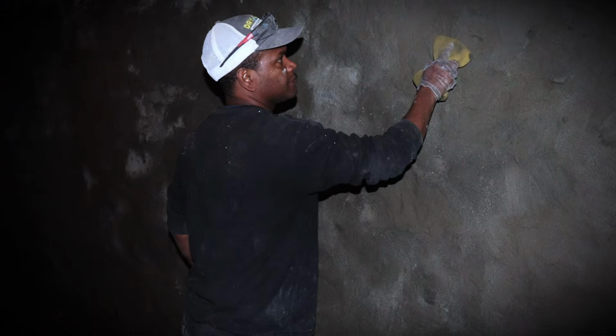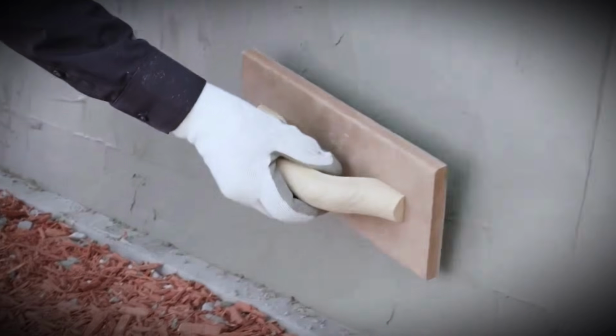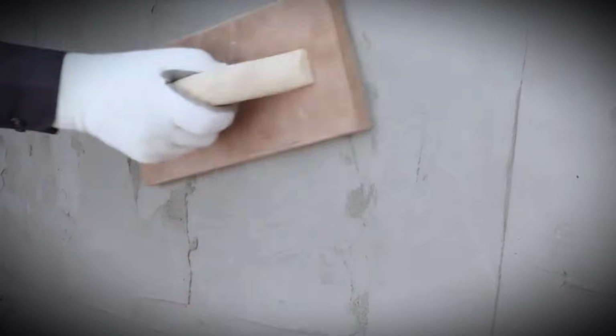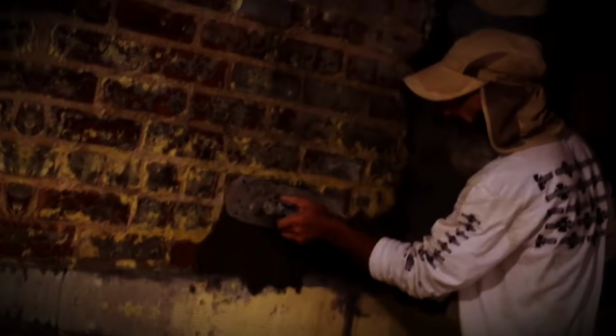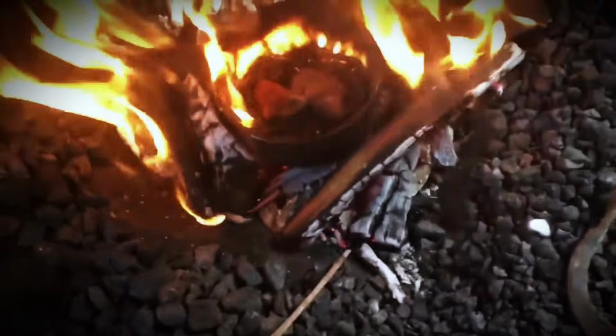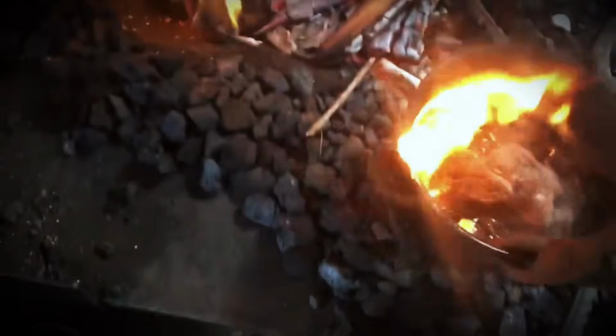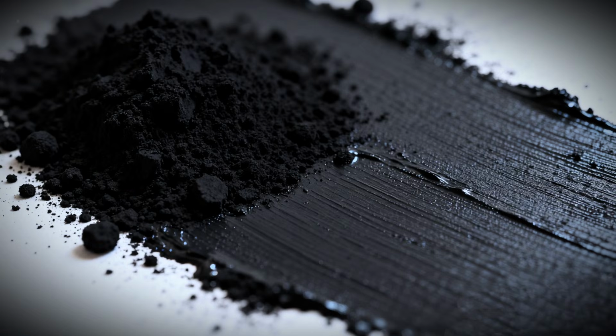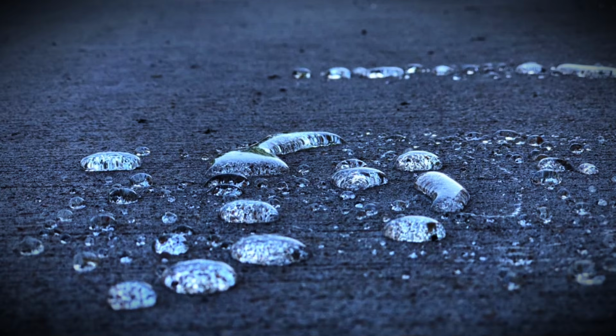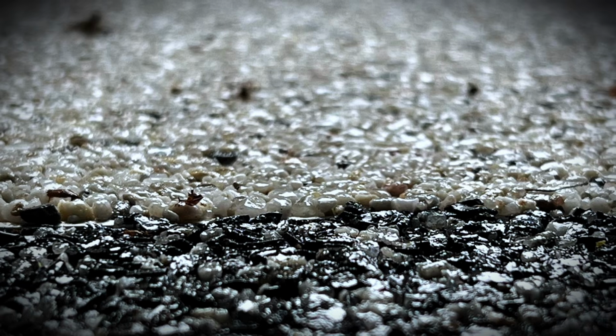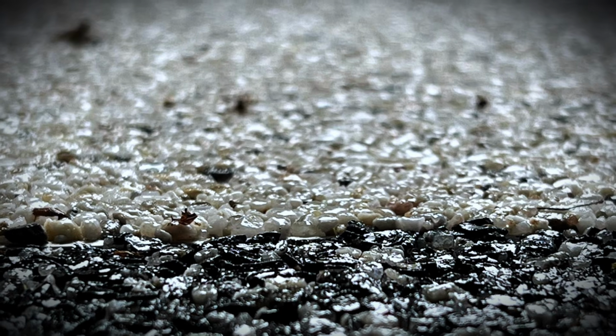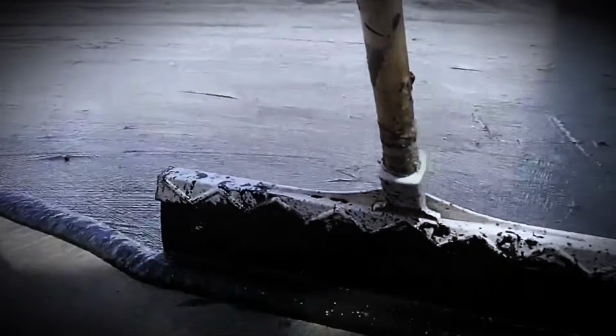thick. The first coat went on rough. The second coat was smoothed and beveled at the top to create a wash that directed water downward, and thickened at the bottom to form a cove where the wall met the footing. Once the parging cured, the mason or a laborer would brush or trowel a thick layer of hot coal tar or asphalt-based bitumen over the entire surface. This bituminous coating was sticky, pitch black, and completely impervious to water. It bonded to the parging underneath and created a continuous waterproof shell around the entire below-grade portion of the foundation.